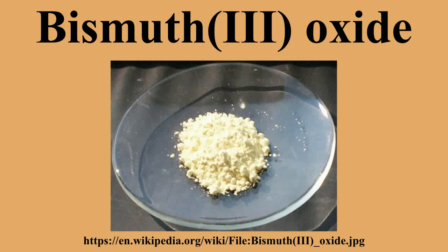Medical device usage. Bismuth oxide is occasionally used in dental materials to make them more opaque to X-rays than the surrounding tooth structure. In particular, bismuth oxide has been used in hydraulic silicate cements, originally in MTA from 10 to 20% by mass with a mixture of mainly di- and tricalcium silicate powders.